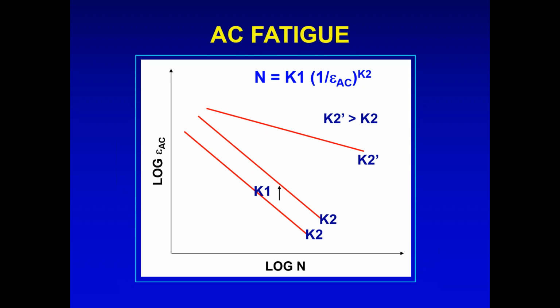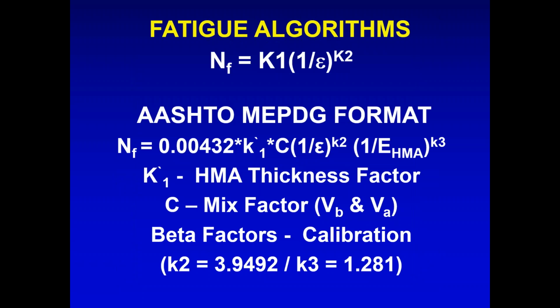You'll see a lot of K2s flopping around out there around 0.5. In this particular fatigue algorithm, that's one we've used and is in the Illinois DOT design guide. The MEPDG has a K2 and a K3 they bring into the equation, the stiffness of the hot mix. It has an effect. The major driving factor, though, is the strain term. That value is basically the one that dominates the fatigue of hot mix asphalt.